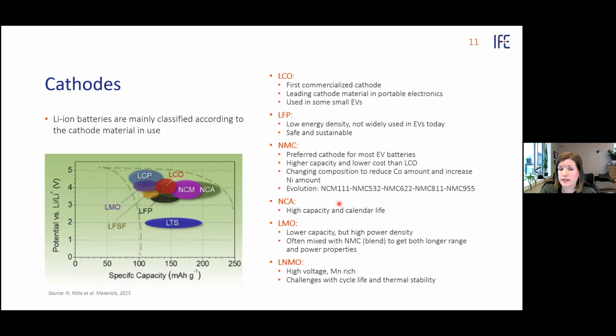Another cathode material is NCA, lithium nickel cobalt aluminium oxide. That's the version that's been found in Tesla cars. It has an even higher capacity and a quite good calendar life. Then we have LMO, which is here. A bit lower capacity, but high power density, somewhat higher voltages. That is often used in a mix together with NMC. It's called a blend battery, where we can get both longer range and better power properties.